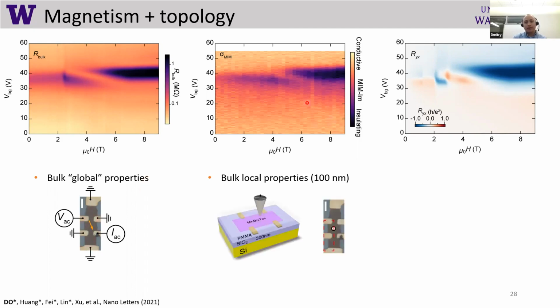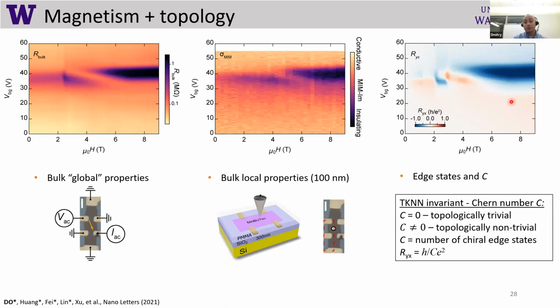This measurement is also a mapping of conductivity, but in this case, not global, but local. So the tip is parked in the middle of the sample, far from the edge. I already spoke about edge states and showed you that they are chiral, but now we are interested in the bulk. So we measure in the very middle of the sample, and we map out the conductivity of the sample locally there. And we can also do regular transport measurements, which inform us on the Chern number.